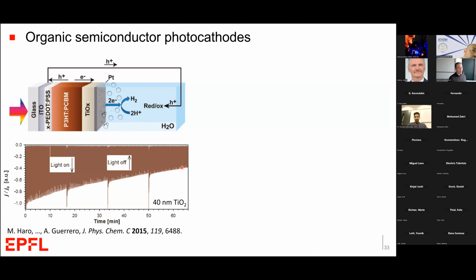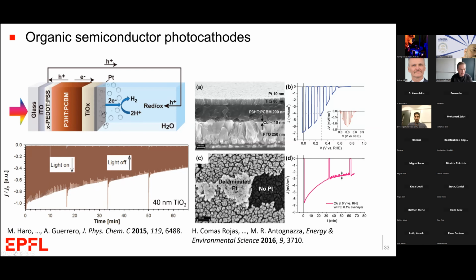Only after an hour, the photocurrent drops by a factor of more than 2. A similar demonstration by another group showed a similar decrease in the photocurrent after only about 1 hour. They attribute this somehow to the delamination of the platinum that's used as a catalyst on the surface. However, I think it's not clear whether these materials themselves, these organic semiconductors, could be stable under these